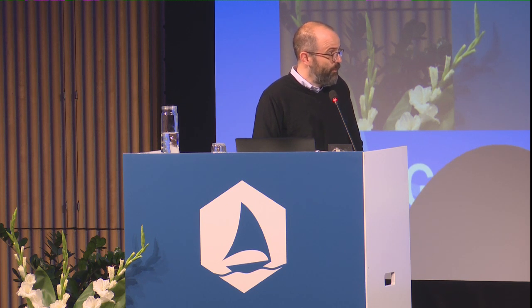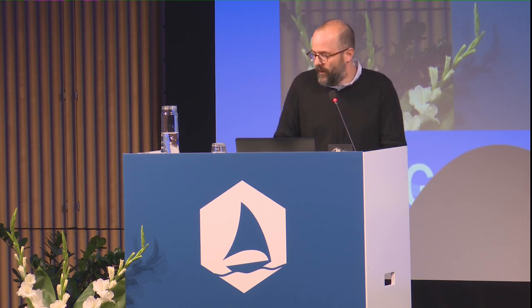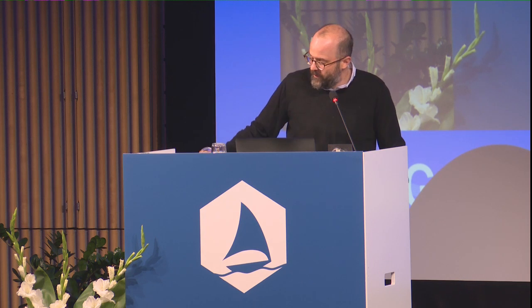So just as a function of twisting this top layer, I'm really modifying this whole band structure in a pretty interesting way. At one extreme, I have gaps at both the charge neutrality point and the satellite point. At the other extreme, I maintain the presence of a superlattice, but I've lost the gap. And we think this is just the argument that I made before. Here I've got inversion symmetry breaking, and here I don't have inversion symmetry breaking, despite still having a superlattice potential.